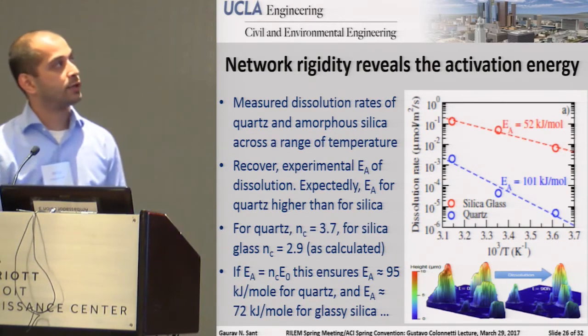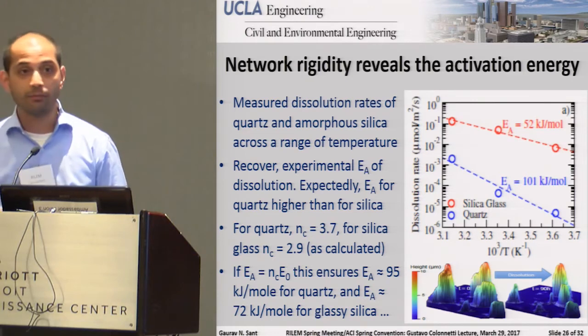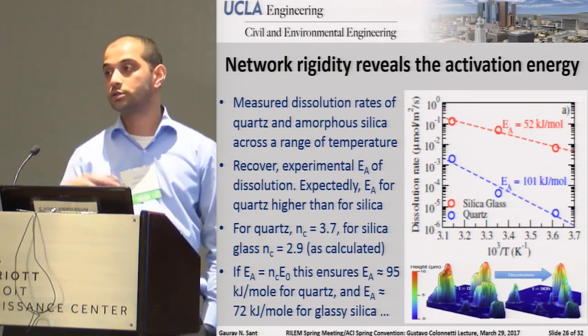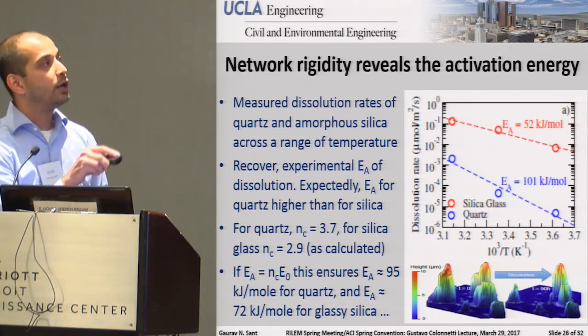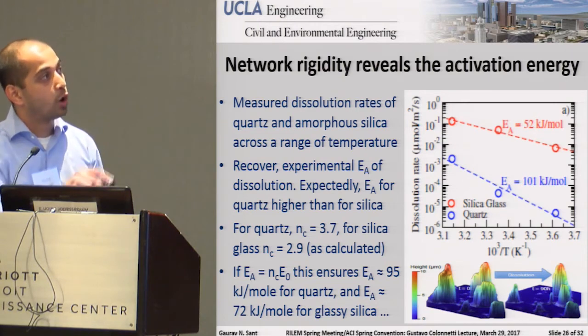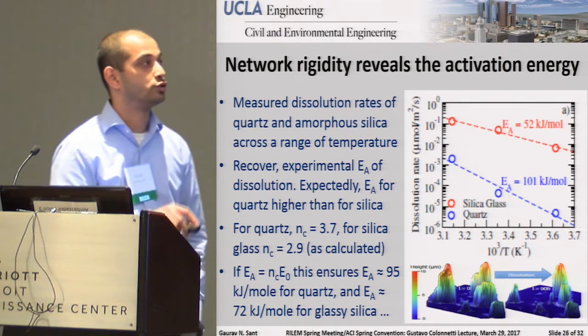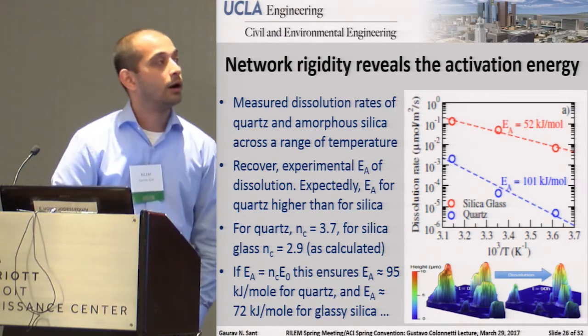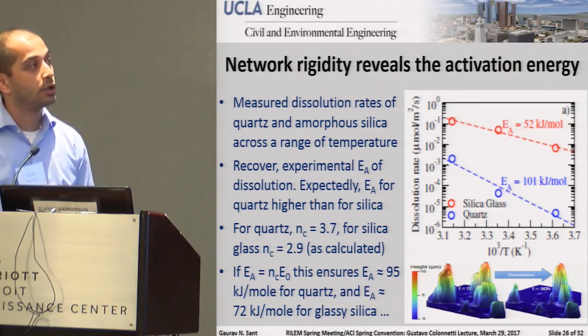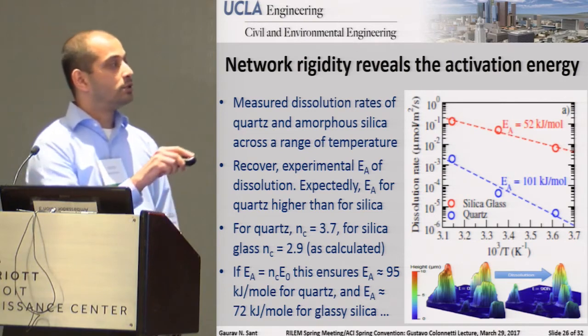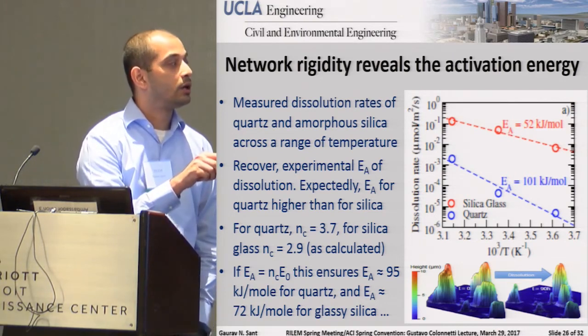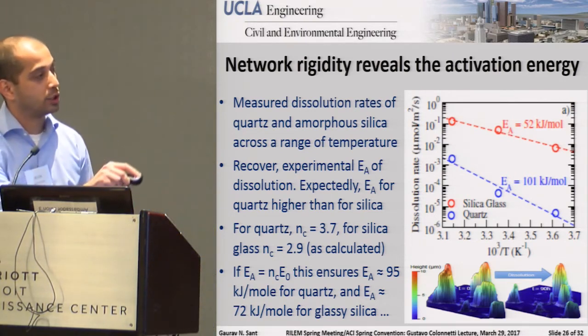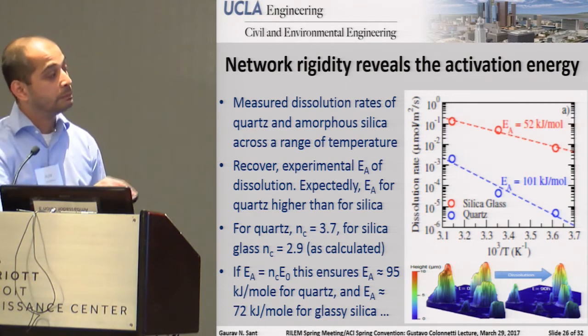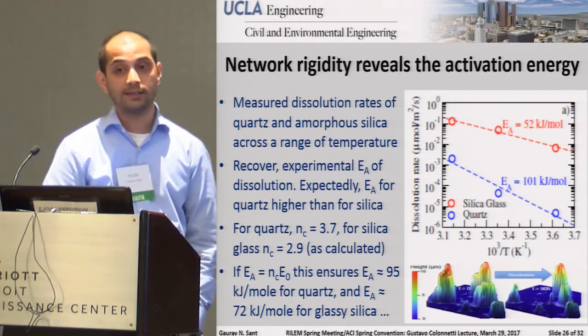So we measured the dissolution rates of quartz and amorphous silica across a range of temperatures, essentially going from, I think, 5 degrees Celsius to 65 degrees Celsius, and we looked at what the activation energy of dissolution was. For silica, we see an activation energy of dissolution of about 52 kilojoules per mole. For quartz, we see an activation energy of about 100 kilojoules per mole. When we do this NC times E-naught business, we determine that the activation energy for quartz dissolution is about 95 kilojoules per mole and about 72 kilojoules per mole for glassy silica.